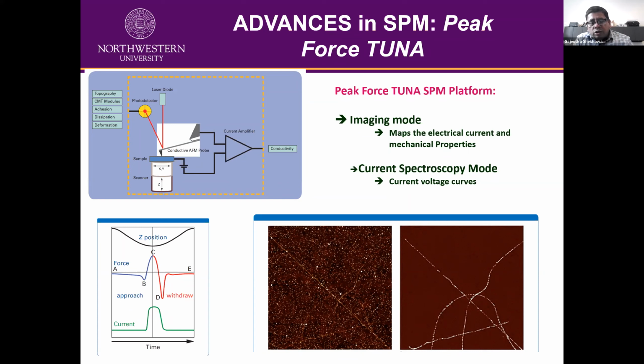And also, given that the cost of these probes is pretty high, they incorporated peak force tapping into this conducting AFM. Now it's called PeakForce TUNA, where obviously the probe is applying a pretty low force, so you can sustain a longer lifetime of these probes with the metal coating, and you can get high resolution images.